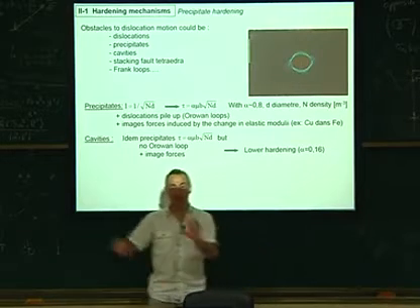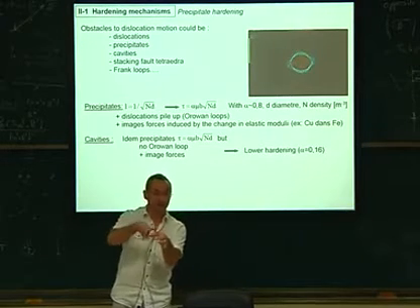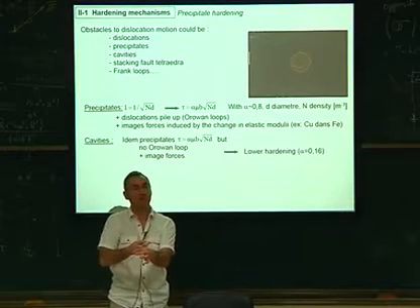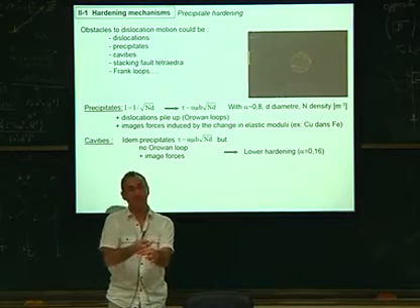Exactly. Dislocation comes into the void, it's attracted, and it is pinned there. Now you need to take the dislocation out of the void. So you need to create fresh dislocation length. And this has a cost.